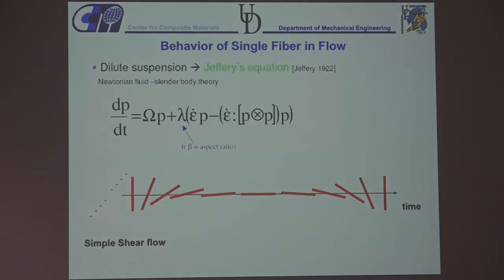So very early on, we said, okay, we want to be able to predict the fiber orientation and flow. So this is an equation that was developed by Jeffery in 1922 for a single fiber of how it rotates in shear flow. So p is the vector that points along the fiber, omega is the vorticity, epsilon dot is the velocity gradient tensor. And so he came up with this equation that allows you with time to see how this fiber will rotate. And most of the time the fiber spends its time aligned in the shear flow and sometimes at the walls. So this was an analytical solution to this equation, and this beta was the aspect ratio of diameter to the length of the fiber.